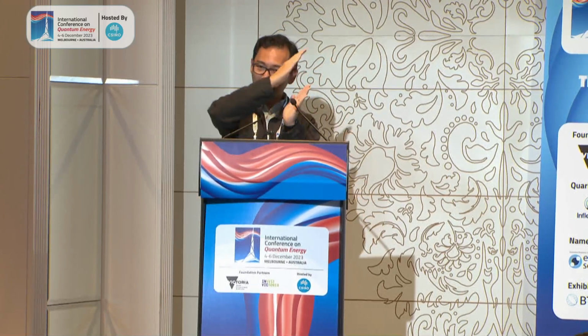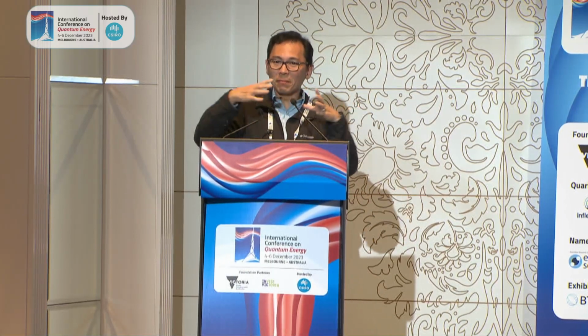Yeah, so the slope basically represents the amount of the coupling. The peaks undergo slight change in the coupling frequencies. When it's more aligned to the diagonal, it has a particular slope, and when it's vibrating, it has more coupling with another molecule or another mode, and then it changes shape. So by analyzing that, we understand all sorts of different couplings. The Huang-Rhys factor out of that? Correct. Yeah, the Huang-Rhys factor of the molecule. Thank you.